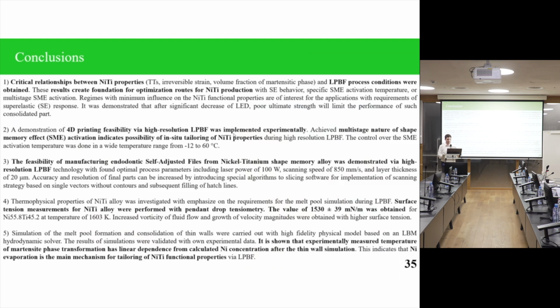All main conclusions of this research are presented on this slide. So critical relationship between nitinol properties and laser powder bed fusion conditions were obtained. Then 4D printing feasibility was implemented experimentally by introducing a multi-stage shape memory effect in a single sample without any additional heat treatment.